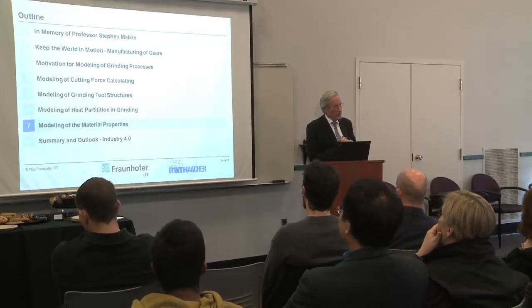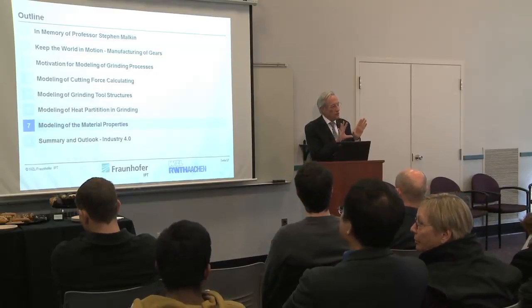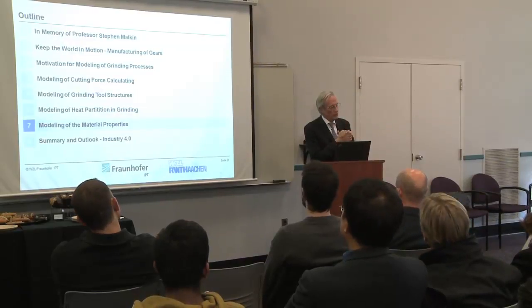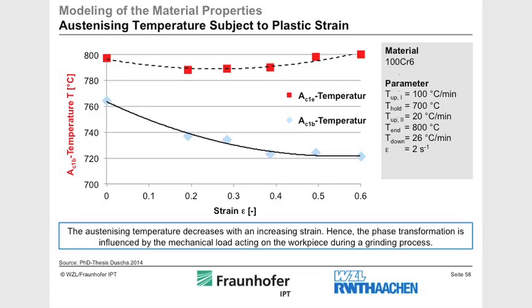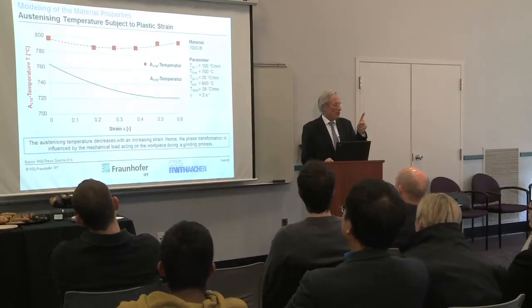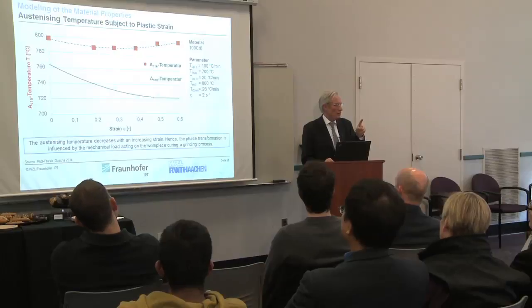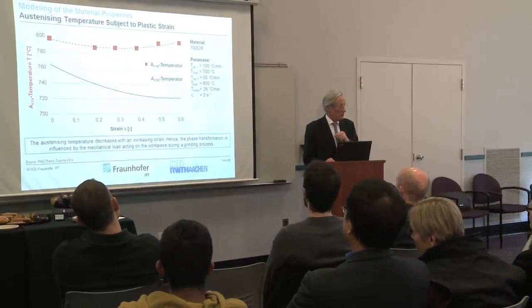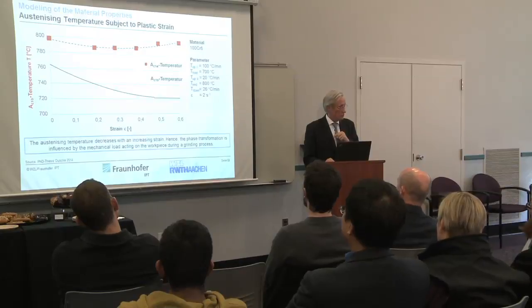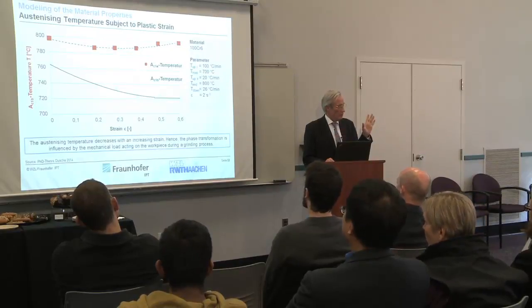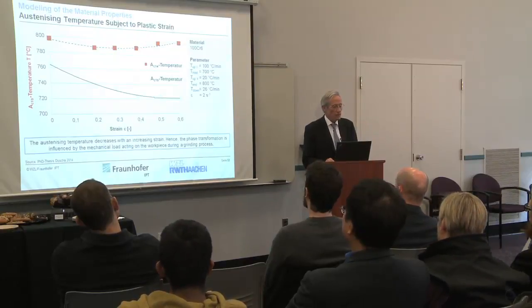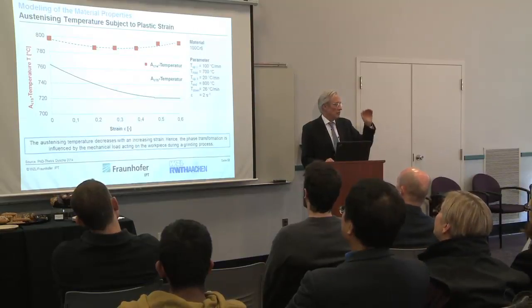Okay, so as we now know what the mechanical conditions are, so we know the cutting force components, we also have some clue about the pressure. And we have our material, and we know the material properties, and what this slide just shows is that the temperature at which phase changes occur is dependent also on the stress conditions, on stress and strain. So if there was no mechanical stress and strain, in this case 760 degrees centigrade, change to austenite. And under real grinding conditions, you see this temperature drops down.